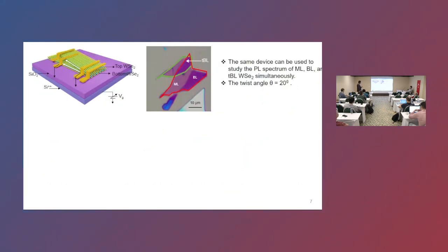Okay, so that's the device structure. We twisted two WSe2 layers on top of each other, did lithography to make the leads, and made a back gate. The silicon dioxide itself is a dielectric, so we use the silicon dioxide to dope the system, okay?